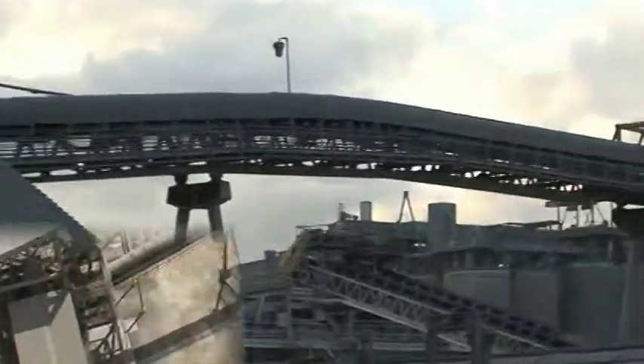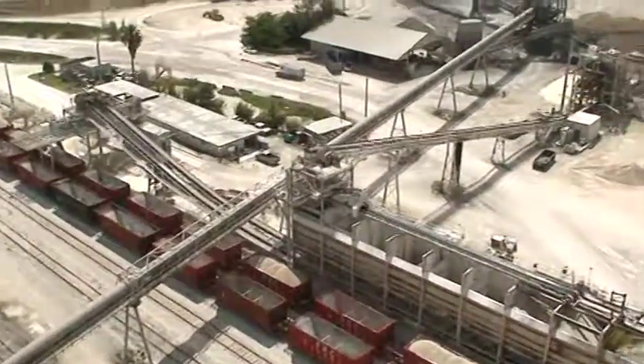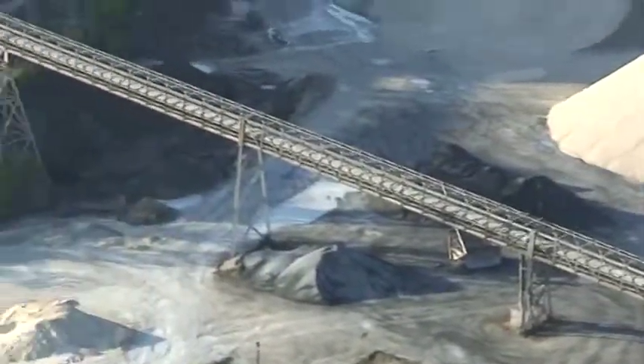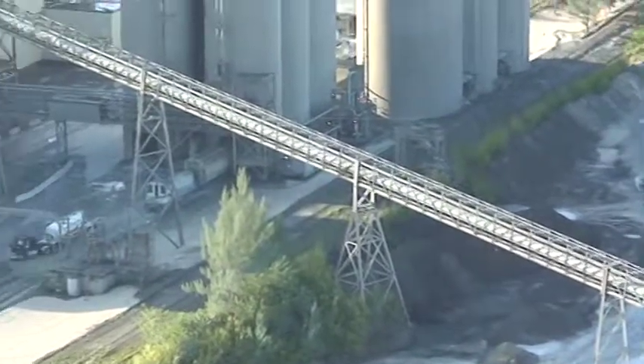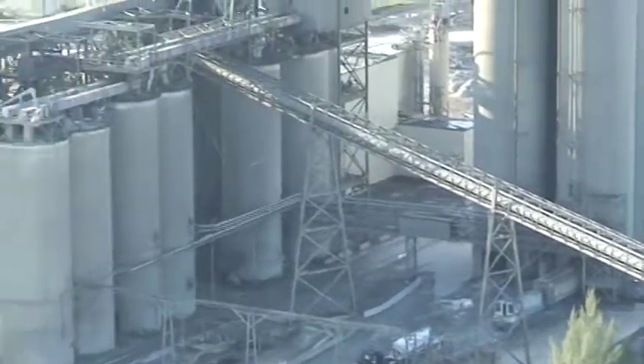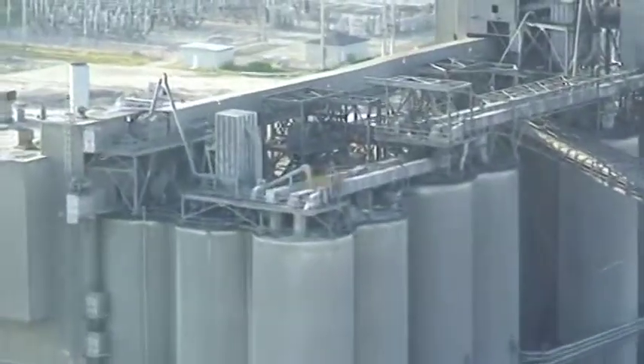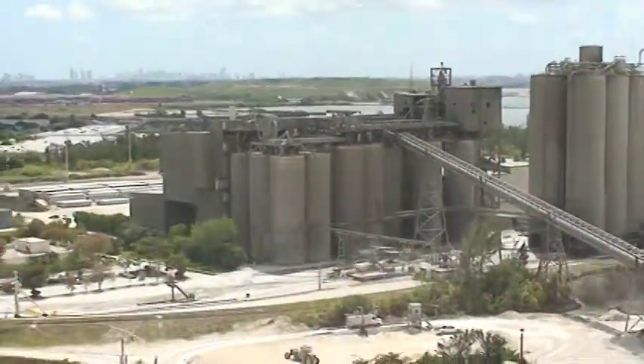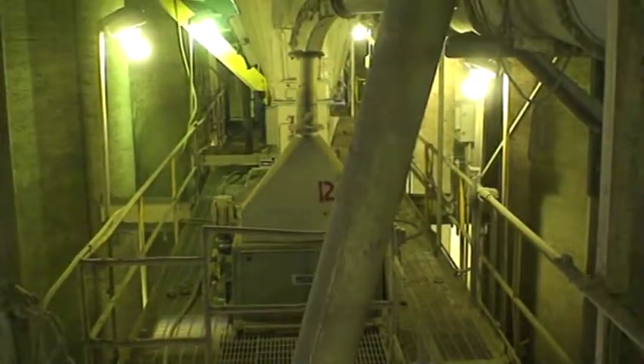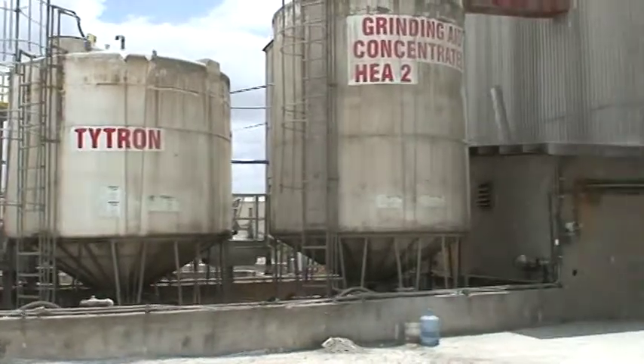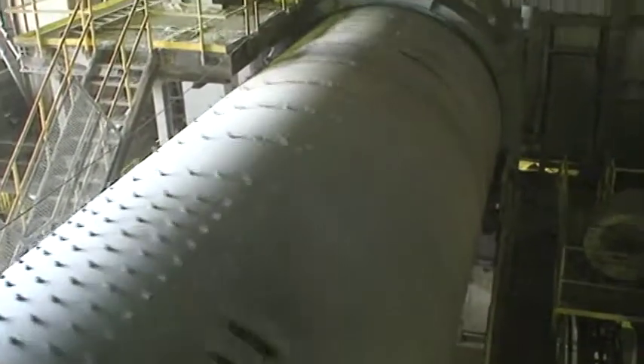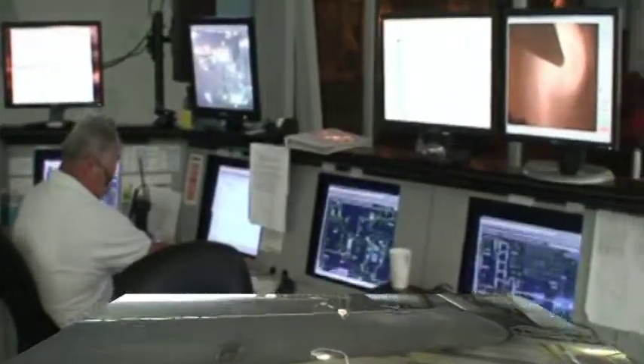Material is extracted from underneath these silos and flows on a series of conveyors up and over to the top of the mill building. Clinker mixed with 5 to 6% gypsum and various additives are fed into one of 4 finish mills with the combined capability of grinding up to 335 tons an hour. Type 1, Type 1-2, masonry, and stucco are the current products being produced. Masonry and stucco also use limestone.